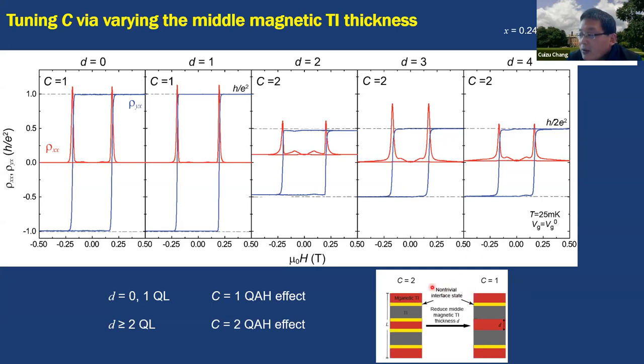We can use this picture to understand it. When the interaction is strong, these two quantum anomalous Hall layers become one quantum anomalous Hall layer, so this is just the C equals 1 quantum anomalous Hall effect. When the interaction is weak, it becomes two quantum anomalous Hall layers, so it shows the C equals 2 quantum anomalous Hall effect.